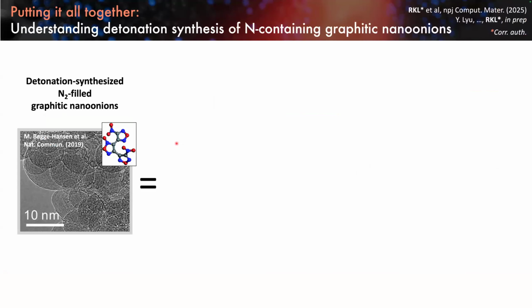In the beginning of this portion of the talk, I discussed this molecule called DNTF that, when detonated, forms these graphitic nanoonions. If you look carefully at this TEM image, you'll see these concentric rings - those are the layers of the graphite shells. If you look carefully, it might be difficult to see, but these particles also have a core to them. You can see that there and over here.